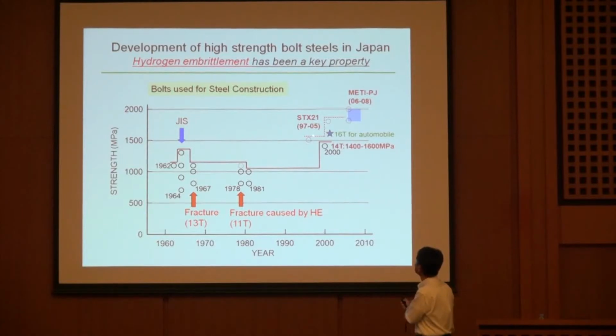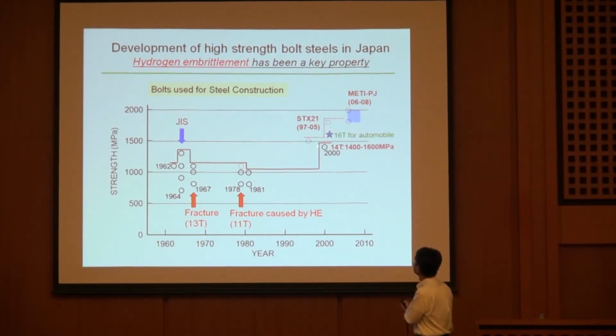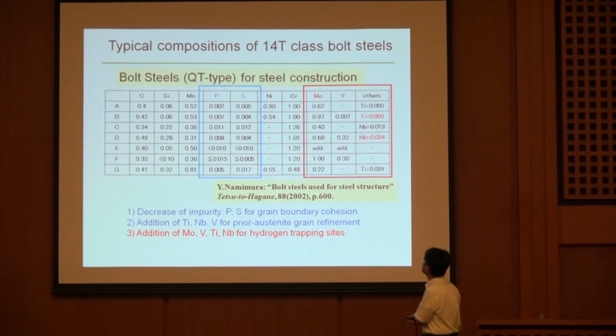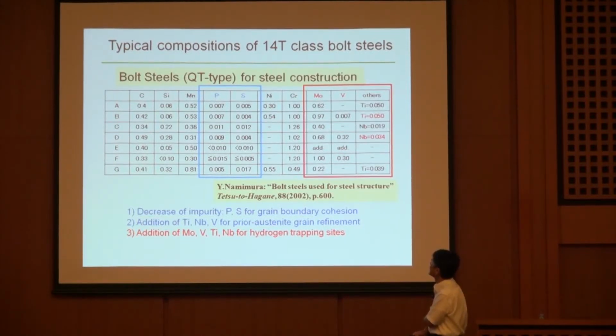Here is a jump. Actually, this is pulled by automobile products, automobile bolts, like this. And this jump is associated with the addition of alloying elements such as molybdenum, vanadium, titanium, and niobium. Okay? And with low concentration of impurities of phosphorus and sulfur.